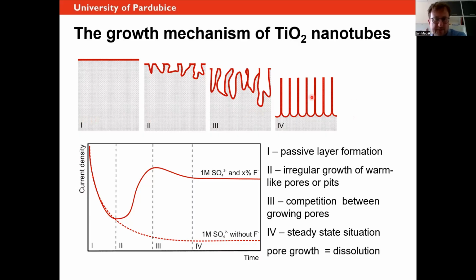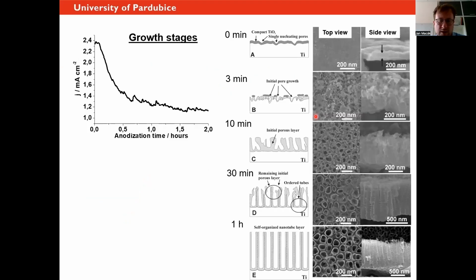So this is also the state of the energy which has the lowest entropy. And so this takes about 1 hour, 2 hours. And if you really want to get rid of HF and if you really want to understand the process, you have to try to understand the growth in really, really good detail. And that's actually what we did.